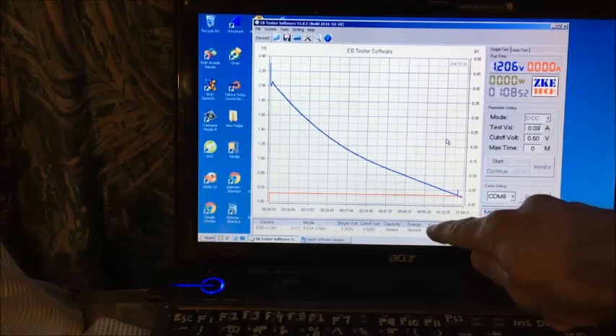In between, the rehydrated zinc plate cell had an hour and 20 minutes charge and produced 38 milliwatt hours, with a 1 hour run time at 30 milliamp load. So it's still a valid cell after being dried out for at least a week and a half. There was no electrolyte added to it. Alright, I'm going to check the carbon.